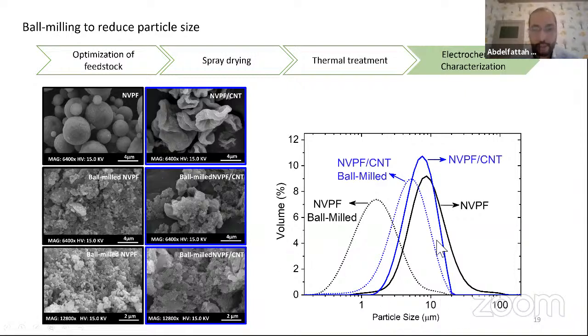by decreasing the particle size from 10 to more or less 1 for NVPF, and something like 5 for the composite, because it's hard to decrease the particle size of the composite material with carbon nanotubes, as carbon nanotubes form a very rigid network around NVPF particles, but even then we decreased it almost to the half.